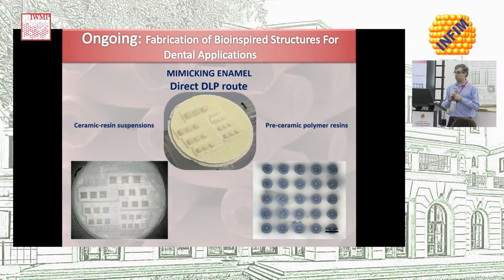So we have only been able to produce relatively large structures, around the millimeter scale, so not good enough. So we are trying the direct DLP route, in which we have either ceramic resin suspensions or pre-ceramic polymer resins, and then we print the structures, and as you can see there, we can produce features below the 100 micron range.